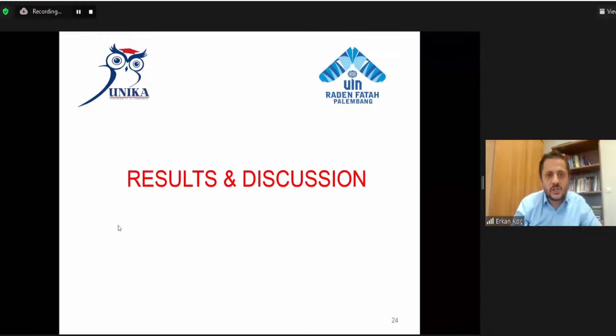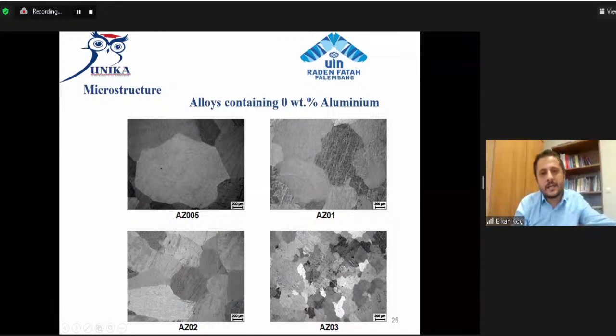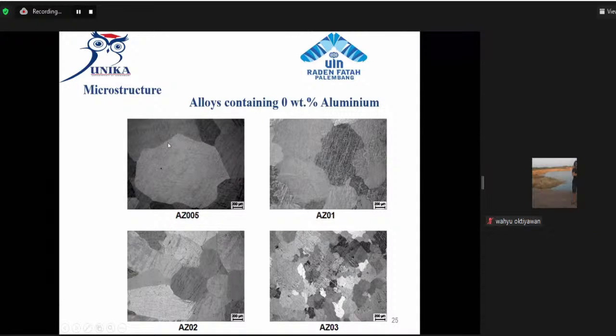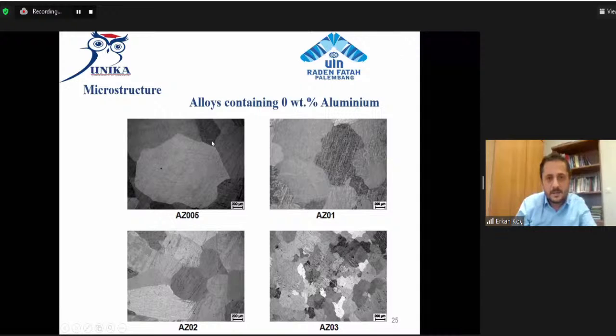Our results and discussion: alloys containing 0 aluminum, it means magnesium plus zinc. AZ 005 means 0 aluminum, 0.5 weight percent zinc, and the rest magnesium, and then 1 weight percent zinc, 2 weight percent zinc, 3 weight percent zinc. And experiments show that as the amount of zinc element increases, the grain size of the magnesium decreases.